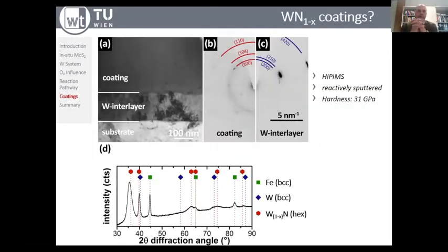So we said, okay, fine, but who is using, by the way, pure tungsten surfaces? No one. Also, there is a problem with the tungsten delivery. So we saw that in the case of MoS2, molybdenum surfaces are more voluntarily forming MoS2 in situ. In the case of tungsten, there are some complications. And also in terms of, as I said, the delivery system of the tungsten, there are some drawbacks. So we decided to go for tungsten nitride coatings.